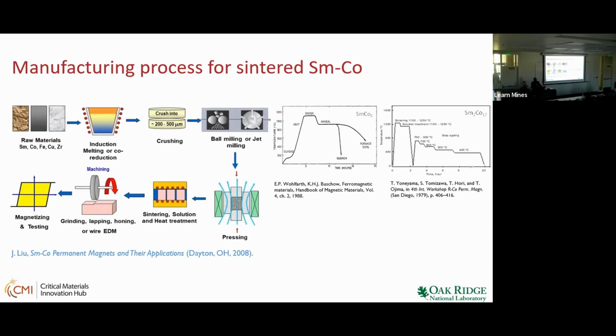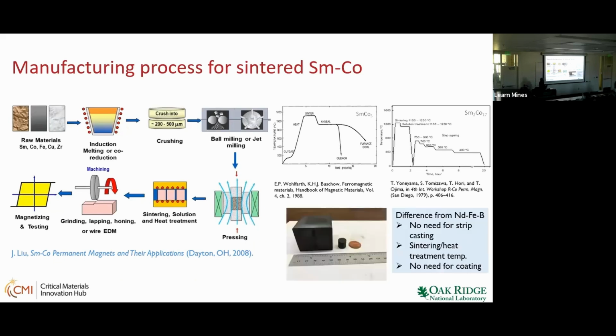So these are the two compositions you do. Then finally you do the pressing, sintering, grinding and magnetization. So that's like a standard process you can do. And once you make the magnet, it looks something like this. One good thing about samarium cobalt is it has a high Curie temperature. A lot of aerospace applications, sensors and all those things, they prefer samarium cobalt, even though it's a little bit weaker compared to neodymium iron boron.